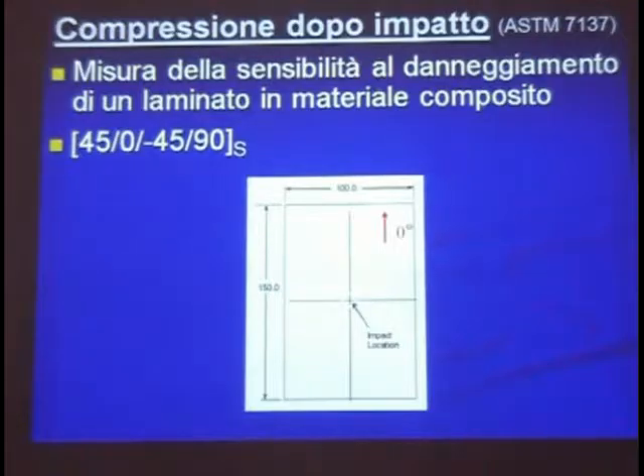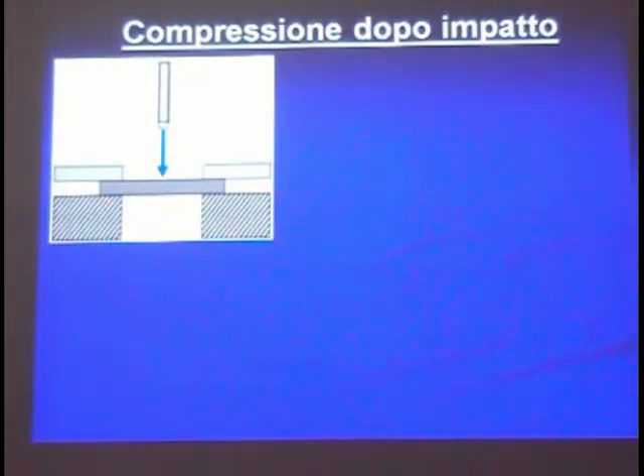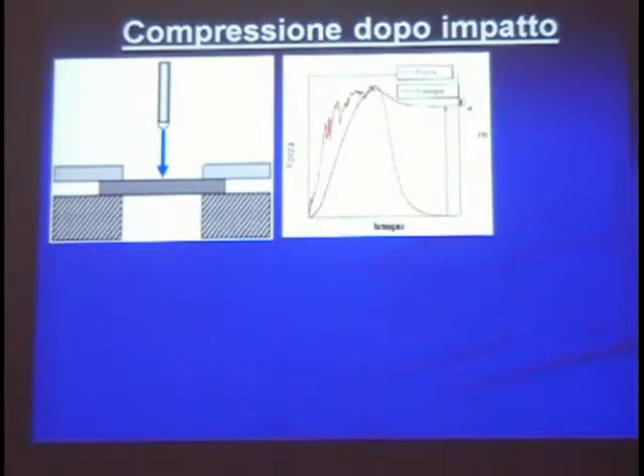This is the way we measure the effect of the processing cycle, using a quasi-isotropic sequence, 45/0/-45/90 degrees symmetric laminates, 8-ply, which has been tested at the center. It is a rectangular specimen, 100 by 150 millimeters. This sample is tested in impact with an energy which is not sufficient to break it, but simply to damage it. So the striker rebounds, and after the rebound, one can calculate the energy due to the impact.